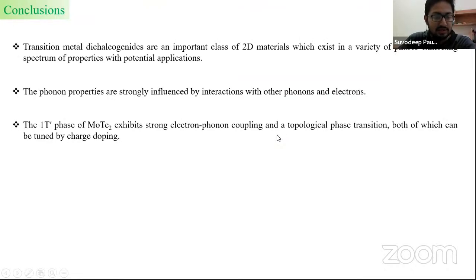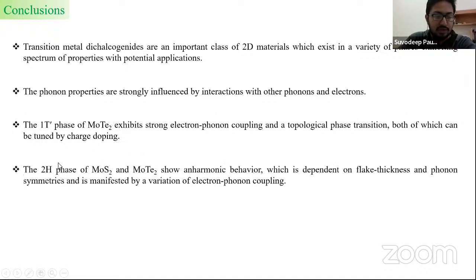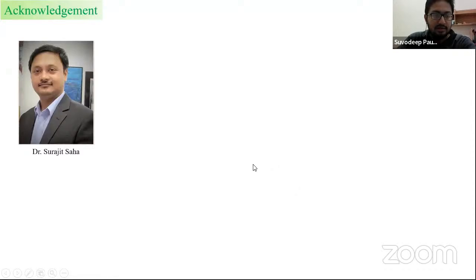So with that, I'll come to my concluding remarks. Mainly, we have studied the 1T prime phase, which shows a topological phase transition and electron-phonon coupling, both of which could be tuned by charge doping. The other study that we performed was on the 2H phase of MoS2 and MoTe2, and we saw the anharmonic behavior to be dependent on flake thickness and phonon symmetries, and electron-phonon coupling also played an important role in the understanding of these behaviors. So with that, I come to the end.